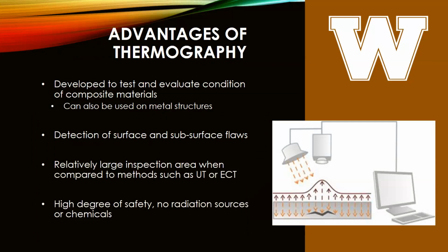It was developed primarily to test and evaluate composite materials. Composite materials are fairly limited in what techniques can be used on them. Right? We can't use magnetic particle. We can't really use liquid penetrant because liquid penetrant soaking into fibers and that kind of thing on composites isn't a good situation. We can't use eddy current testing because most of them are non-metallic. We can use ultrasound, but there's some limits. As I mentioned, it's a non-homogeneous material, and so you get a lot of those acoustic interfaces and weird echoes going on. So though ultrasound is commonly used on composites, it does have its limits.